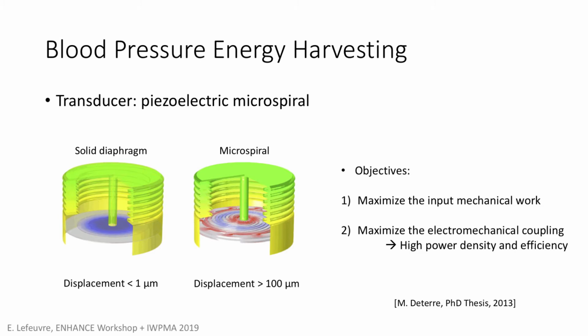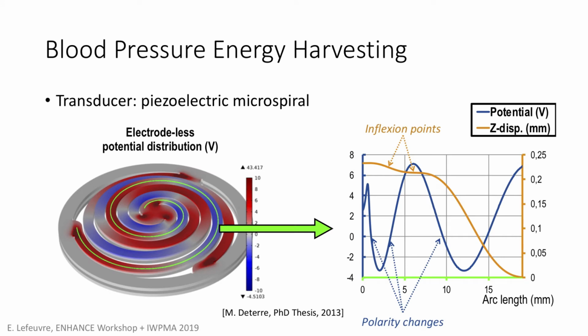So this way, we thought it was a good way to maximize the input mechanical work. And then we had to maximize the electromechanical coupling in order to have a high power density and good efficiency of the device. So that was a very interesting work. I won't give the full details on the design procedure because it's a bit boring, but I'll just show you here a finite element model that we did to study how it behaves. And the graph on the right: the orange curve gives the displacement along this green line, and the blue curve gives the surface potential along the same line.